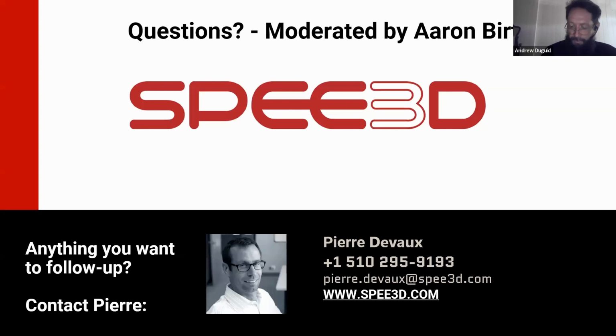It's heaps simpler. With the aluminium bronze, we got very poor deposition behavior for a range of different, more or less alloyed conditions. In addition, it's not a particularly favorable sintering alloy. It has a very narrow freezing range, which means it's very touch and go taking it up to a high temperature and getting it to weld itself together. So for us, in that context, it works better on every level to blend, for instance, the copper and the aluminium together, knowing that when we heat that up we get a transient liquid, formed first by the interalloying of the copper and the aluminium. So, compositional melting, for anybody who knows powder metallurgy. And then the aluminium just melts outright because the temperature is rising so quickly. That works fantastically for us.